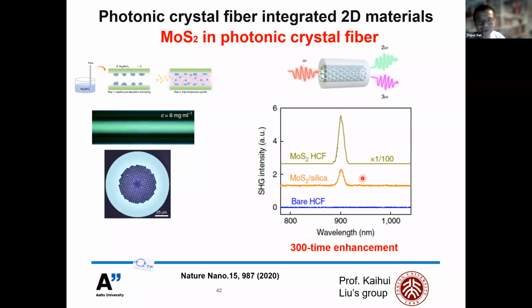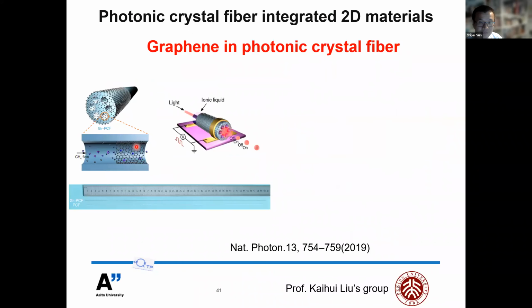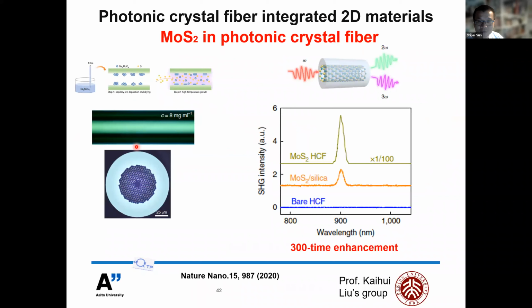Here you will find the second harmonic generation and third harmonic generation results. With the bare photonic crystal fiber, we didn't see any second harmonic generation. This is because silica doesn't have a second-order nonlinear response. If you compare the MoS2 inside the photonic crystal fiber with the MoS2 directly on the silica substrate, for the structure we are showing here, you will find that we could get more than 300 times enhancement of the second harmonic nonlinear response.